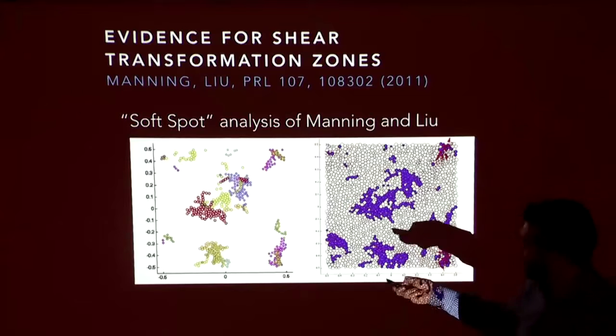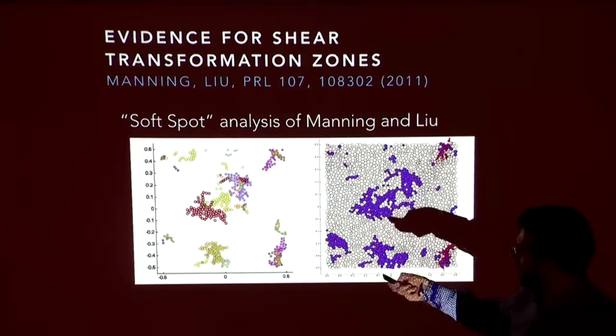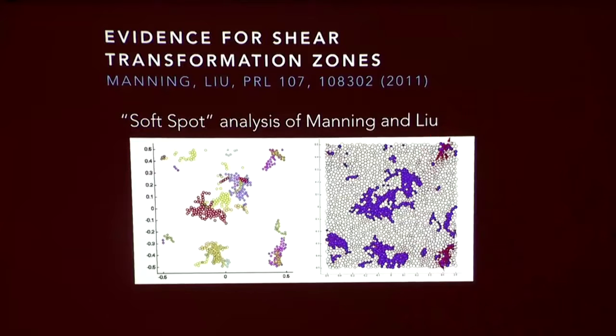So the idea was that this was one soft spot, and this was another, and this was another. And then when she was looking for correlation, she was very strict with herself about having the region that rearranged correspond to one and only one soft spot, which I think is a very strict criterion and kept her correlations rather low. And in my estimation, the places you get deformation do correlate very highly with the atoms that participate disproportionately in the low-frequency eigenmodes, but the ability to cluster them and know which are discrete soft spots, I don't think that was successful.